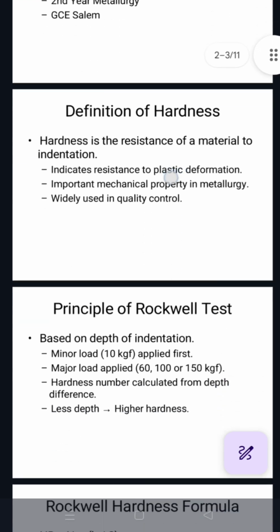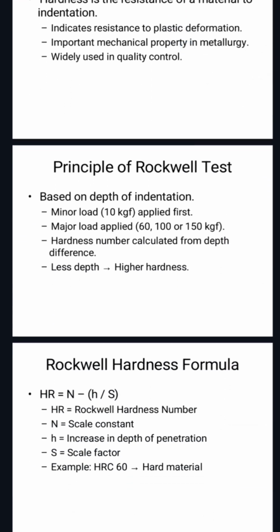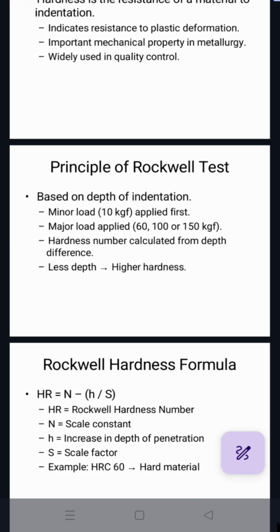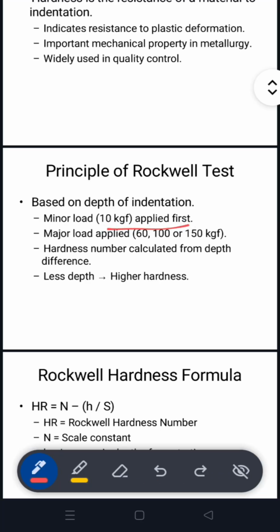Now, let us see the principle of the Rockwell hardness test in our third slide. The Rockwell test is based on the depth of indentation, unlike other hardness tests like the Brinell hardness test, where we measure the diameter of the indentation. In the Rockwell hardness test, we measure how deep the indenter penetrates. First, a minor load of 10 kgf is applied. Then the major load of 60, 100 or 150 kgf is applied. This ensures proper contact between the indenter and the specimen.